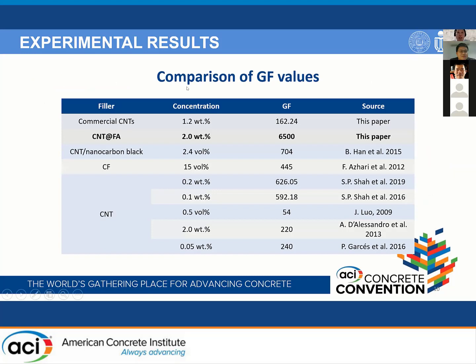Then, in order to further evaluate the sensitivity of the cement sensor in our study, we compared its gauge factor with other cement sensors from the literature, and the results are shown in this table. From this table, we can see that the gauge factor of the CNT and FA cement sensor is the highest among the different gauge factor values. And it is even 10 times higher than the highest gauge factor currently reported in the literature, further suggesting that the CNT and FA particles have a great ability to fabricate cement sensors with an ultra-high gauge factor.